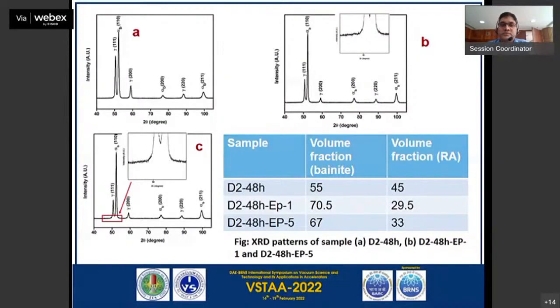By X-ray diffraction, we have confirmed that after isothermal transformation we have only retained austenite and bainite, about 55% bainite and 45% retained austenite. After pulsing once, the retained austenite got reduced, and we can see the bainite quantity increased to about 70%. Now, we could not detect in X-ray the presence of this.